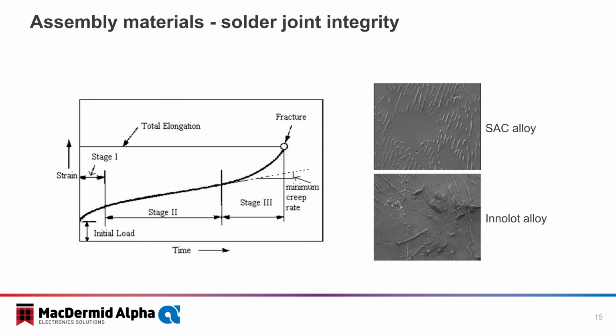Again, the best way to combat solder joint integrity is an alloy enhancement. We alter the alloy movement to reduce fracture. And we do this through alloy development, such as solid solution strengthening, diffusion modifiers, grain refinement, and precipitate strengthening. The Innolot alloy was formulated for underhood automotive applications. A more rigid and reliable material was created through Innolot.